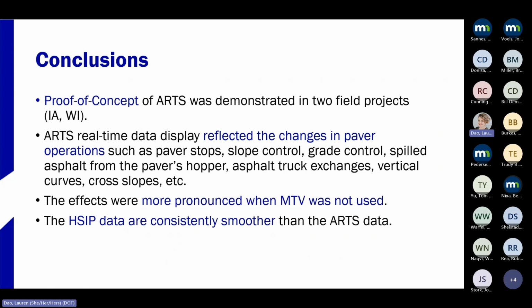This is due to the fact that when you use an MTV, the amount of material in your paver and the head of the material in front of the paver screed are more or less maintained constant. Whereas when you have truck exchanges and you end dump into the paver, the level of the material in the hopper fluctuates a lot more, and there's stopping to accommodate the truck backing up to the paver, which causes more pronounced effects. We also found that the post-compaction surface was relatively smoother compared to the pre-compaction surface.